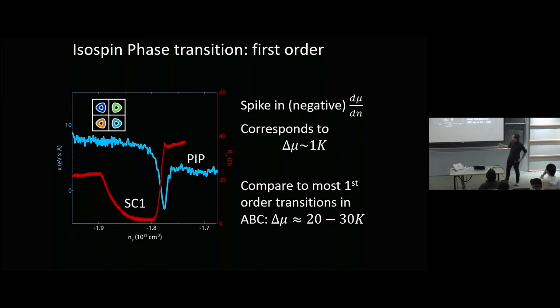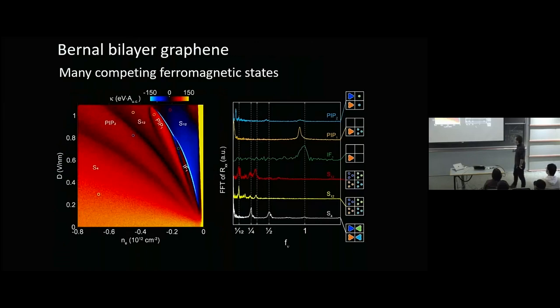Now, it so happens that you go through a Stoner transition into some phase that breaks some symmetries, then you do another transition into a totally spin polarized phase, and then you get superconductivity again in this system from a totally spin polarized phase, and then the same thing happens again. So superconductivity clearly emerges here from a state that, as far as we can tell, doesn't have any broken symmetries. It also can emerge from phases that do have broken symmetries. But as I'll show you, superconductivity is just totally generic in these systems. To me, that points to some generic mechanism, which I'll leave to your imagination.